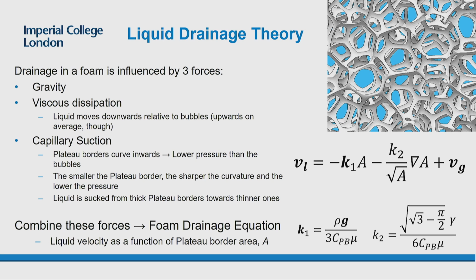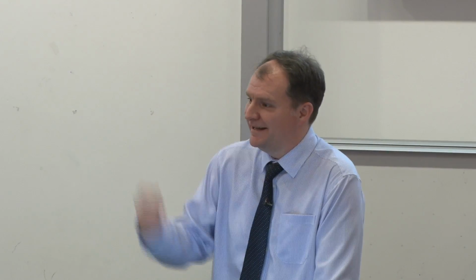Basically, I told you about the plateau borders being curved, and so there's a pressure difference between what's in the bubble and what's in the plateau border. But the smaller the plateau borders are, the bigger this pressure difference. This means that liquid gets sucked from big plateau borders towards little plateau borders, or, to think of it differently, from areas with high liquid content towards areas with low liquid content. And you can combine these three forces to get something known as the foam drainage equation. And this was developed by Denis Weaire and his group in Trinity College, Dublin.